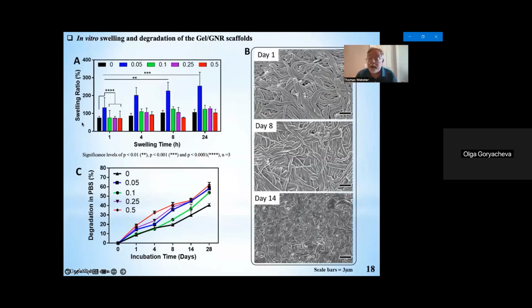Because this is an injectable that we want to inject into the heart tissue, we look at swelling ratio, so different weight ratios of graphene nanoribbons, swelling time. We have pretty good control over that swelling ratio, anything from just below 100% up to 300%, depending on what is needed for the size of the heart damage that occurred after a heart attack. We also can look at how degradation occurs. These materials degrade. Obviously, gelatin degrades. There's also some limited evidence that carbon in the form of graphene nanoribbons can also degrade in the heart. So we have pretty good characterization, and we can tweak this degradation rate to match the growth rate of the cardiomyocytes in the new heart tissue.